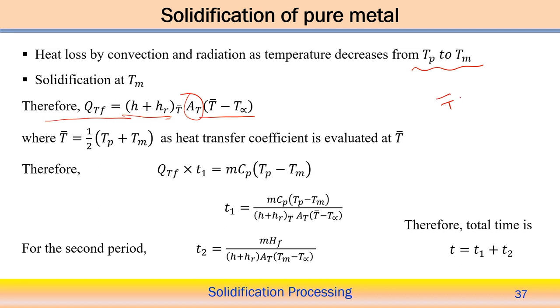T bar is basically the average temperature, (Tp plus Tm) by 2, because we need to decide at which temperature we should consider the values of the heat transfer coefficient. So we have to take an intermediate temperature when going from peak temperature to the melting point temperature. We take all the property values at this average temperature, so at the average temperature we consider the values of the heat transfer coefficient.